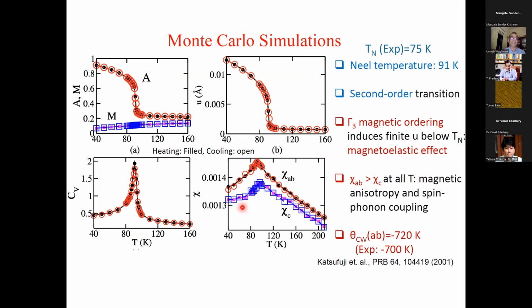Even more challenging were the magnetic susceptibility curves. And indeed, we get agreement with experiment reasonably well. You see our Curie-Weiss temperature is -720 and the experimental value is -700. So this is very encouraging. And in fact, just like in structural phase transition, you have phonons which are unstable. In these systems, it's the spin waves or magnetic excitations which are unstable at low temperatures in the high symmetry phase. And if you invert the magnetic susceptibility, you will see these curves basically will drop to 0, and you will get soft modes. These are called soft spin-on modes, which again become unstable at low temperatures.